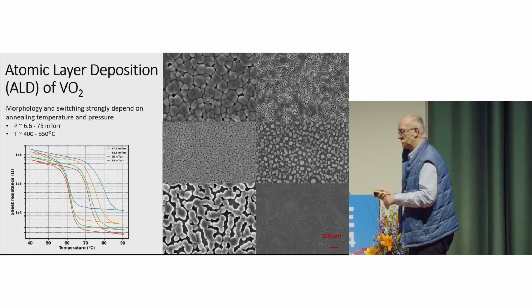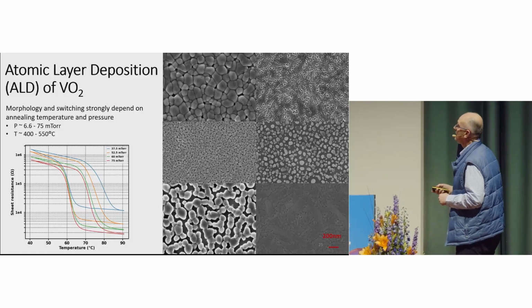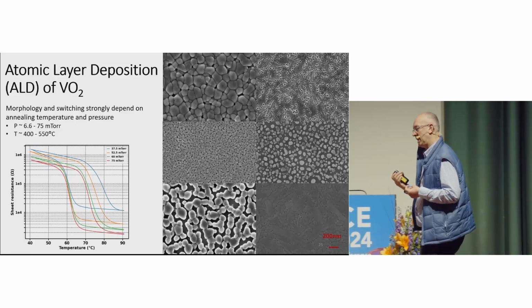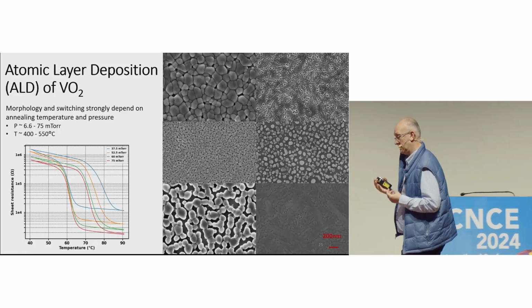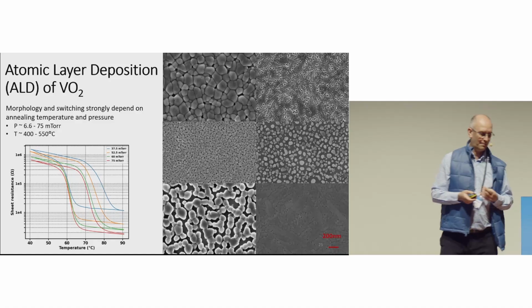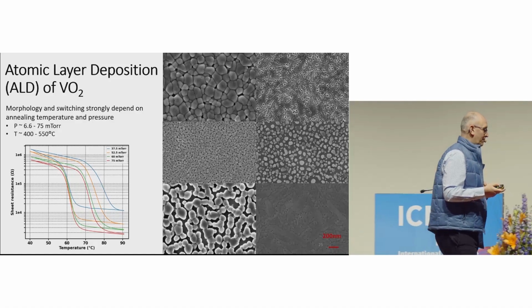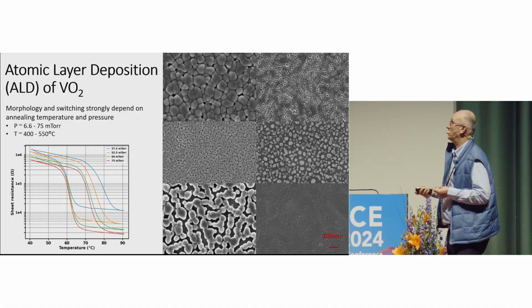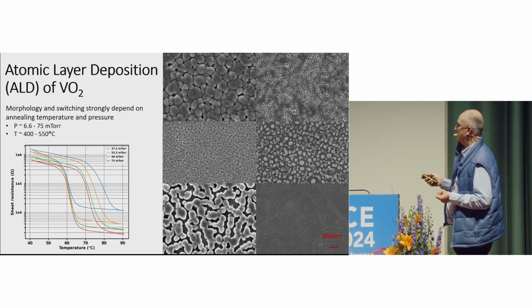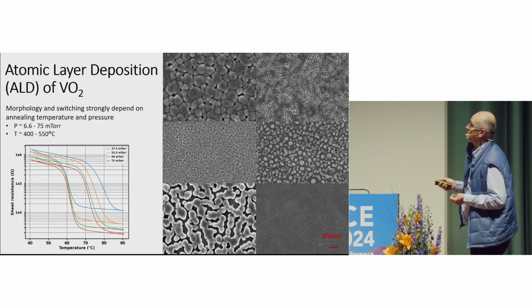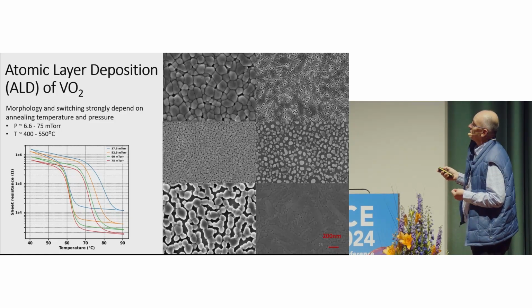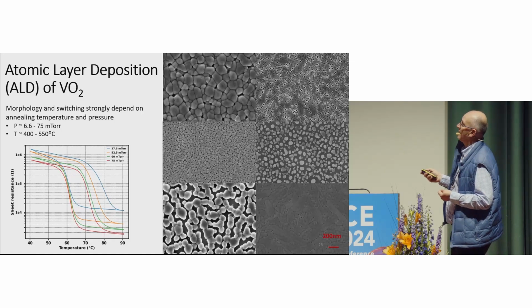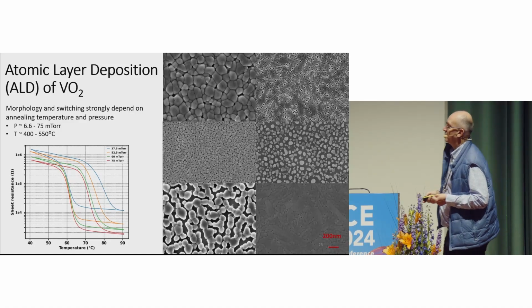Now, my last point, because my time is up, so 2 minutes, is that now we are moving the fabrication of these vanadium oxide-based devices, which were essentially done by sputtering and pulsed laser deposition, to a technique that will make it even more compatible with CMOS devices and structuring devices, which is ALD. So our goal in the next year, and here I'm showing you a first unpublished result, in which the morphology and switching in ALD deposited VO2 that can go down to a few nanometers depend very highly on the temperature that you choose. And we are very near to reaching a similar 3 orders of magnitude.